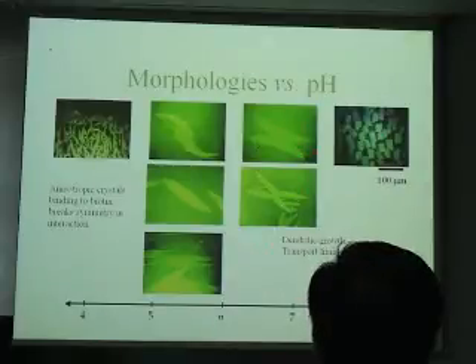So Sue Wong, a student of mine several years ago, found fairly quickly that if you change the pH of the subphase, you got a wide variety of crystalline morphologies reflecting different crystal structures. A previous student, Amber Koo, had already noted that we get very anisotropic crystals. In particular, around neutral pH where we started, we always get rectangular or large X-shaped crystals. And the crystal structure at this pH we knew was square symmetric. It's a square protein and made square crystals, yet they grew faster in one direction than the other. This is due to the fact that 2 biotin sites are bound with biotin and 2 are empty. That very small conformational change upon binding actually changes the protein-protein interaction enough that you get a faster growth in the biotin-bound direction than in the unbound direction.